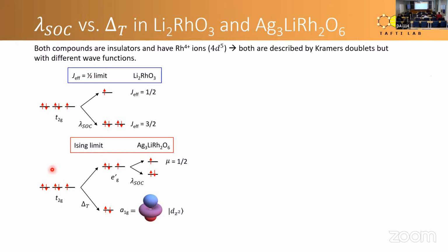In silver lithium rhodate, however, things change. Here you start with the T2G orbitals, but you have a pretty strong trigonal distortion, so that it induces a new crystal electric field. The trigonal compression induces a new electric field, and it further splits the T2G levels into an A1G and an EG prime. The A1G orbital, which has lower energy, is purely a DZ squared orbital. So then all the weight of the X and Y orbitals goes into that EG prime.